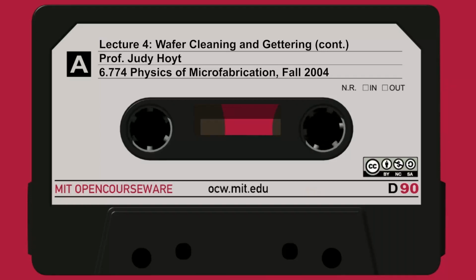And this can happen if you're in a clean room that's not that clean, or if you have particles in your DI water. The last step is a DI water rinse, or if you put it through a dryer, which heats up the wafer and spins it around. And if the spin dryer is very dirty, it can throw particles at the very end throughout your whole wafer. So just to make sure we understand the RCA clean, there's chemistry behind it, but there also has to be a lot of practical things that have to be done properly.